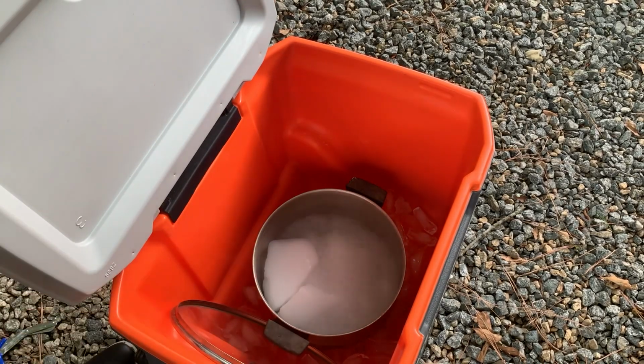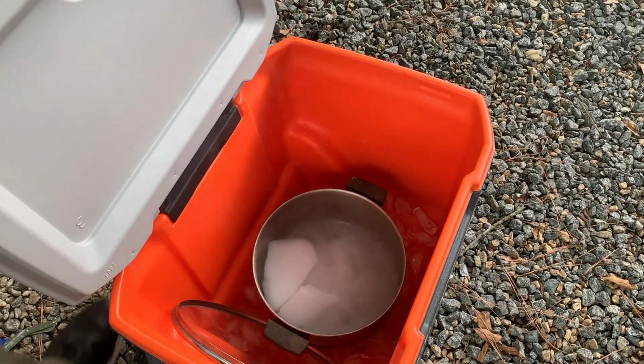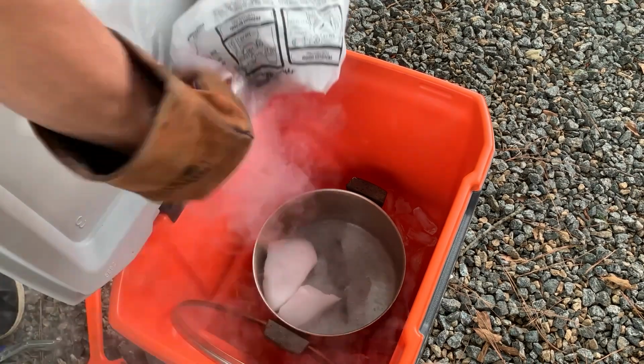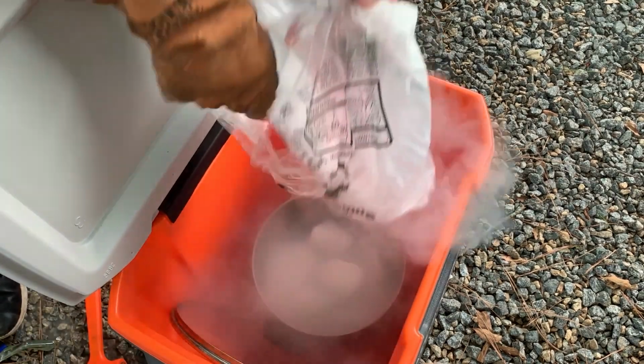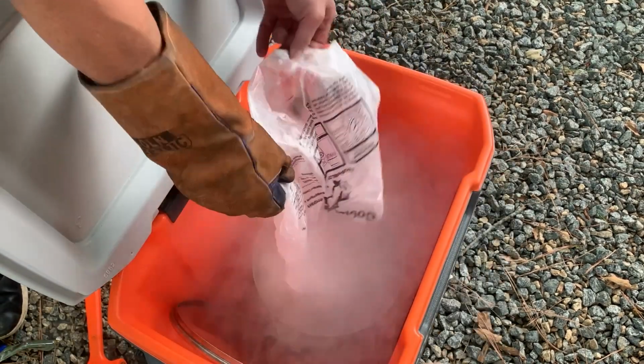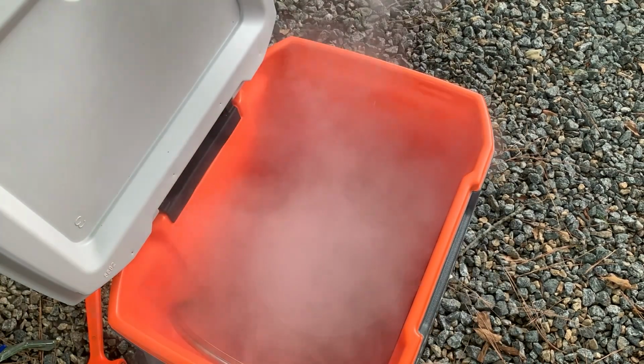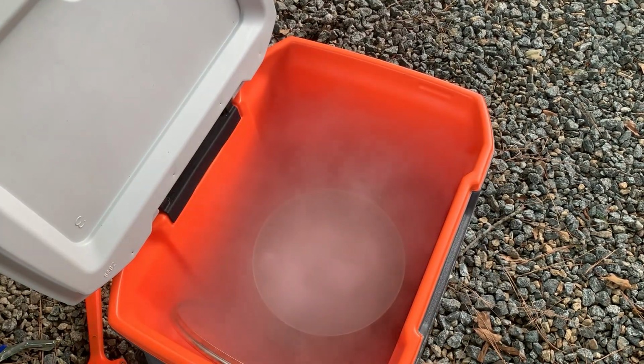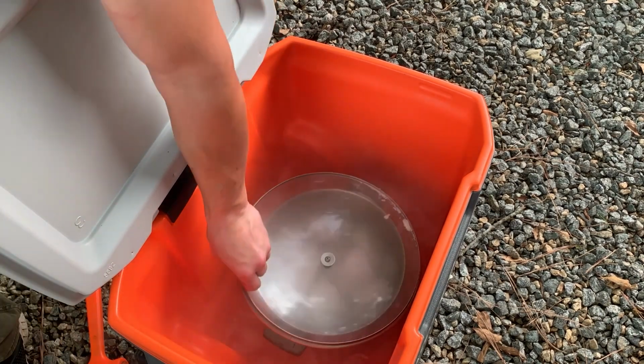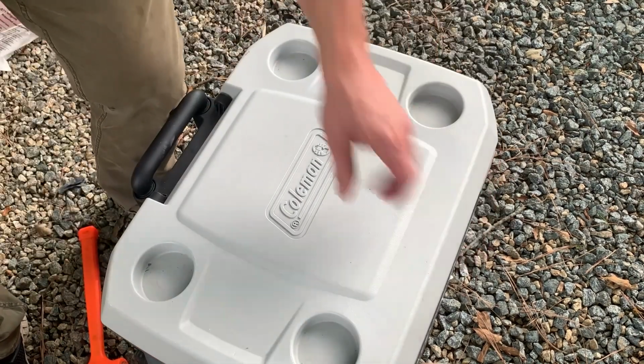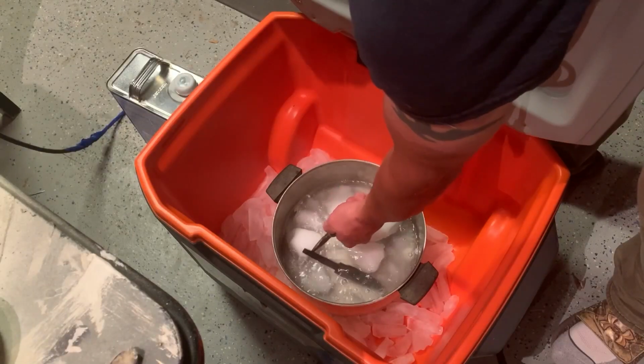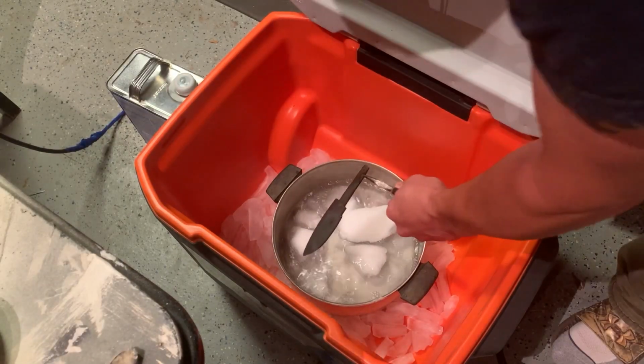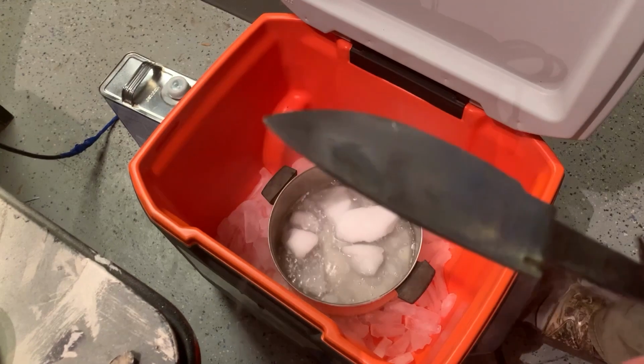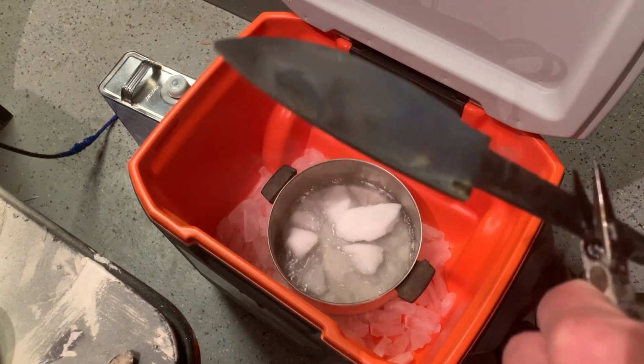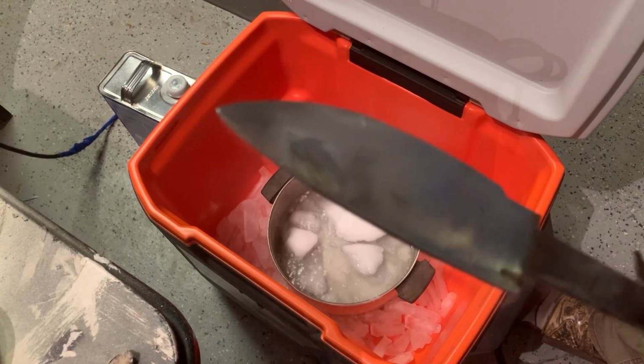Once that's the case, it's time to place it in the deep chill slurry of dry ice and acetone. We often refer to this step casually as cryo, but to truly be cryo it has to be something more like liquid nitrogen, which chills to -300 Fahrenheit. Dry ice goes down to -109, which is still very effective. In fact, according to a scholarly article by Knife Steel Nerds, dry ice is almost equally effective as liquid nitrogen at converting unstable austenite to martensite and further hardening the steel.